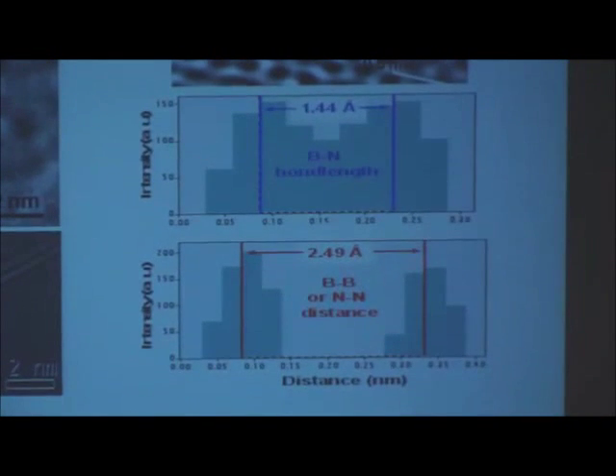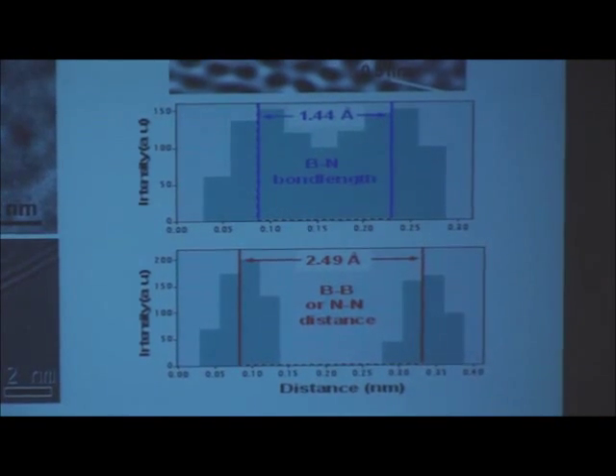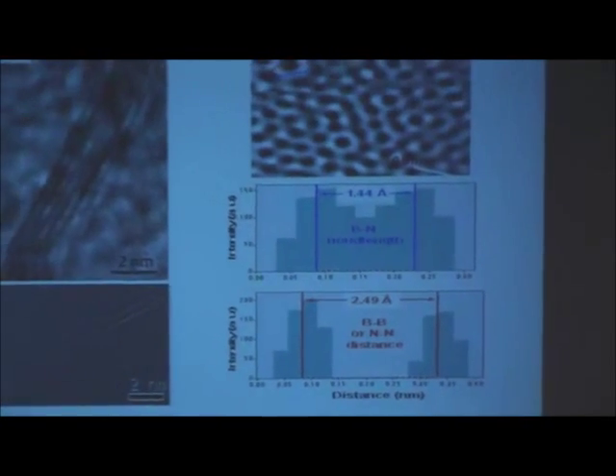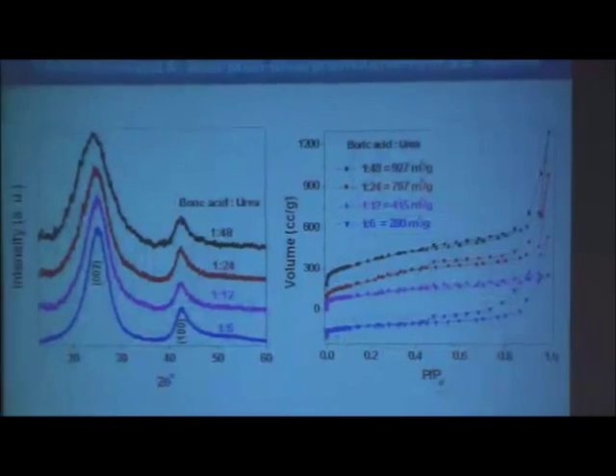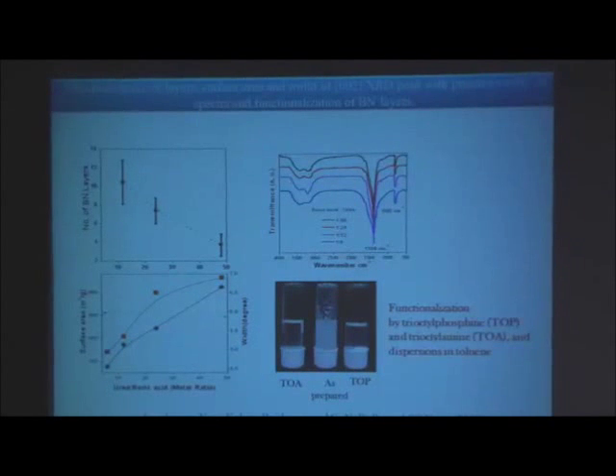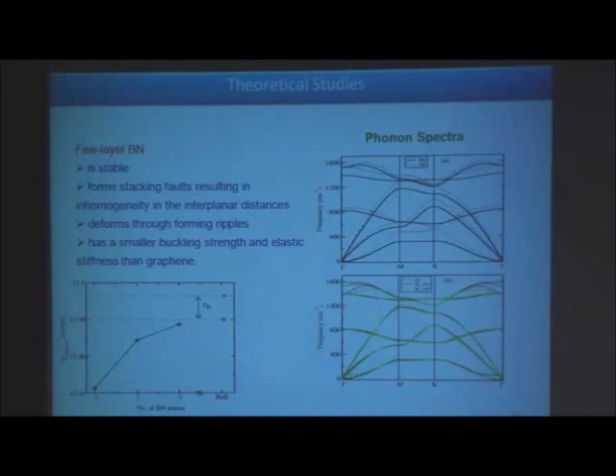This is a high resolution, aberration-free microscope. And so you can get this beautiful image, and you can measure the boron-nitrogen bond distance, boron-boron, all that. And this is a single layer boron nitride. This is something we did recently. And we have also done, we'll forget that, surface area, we have done functionalization.